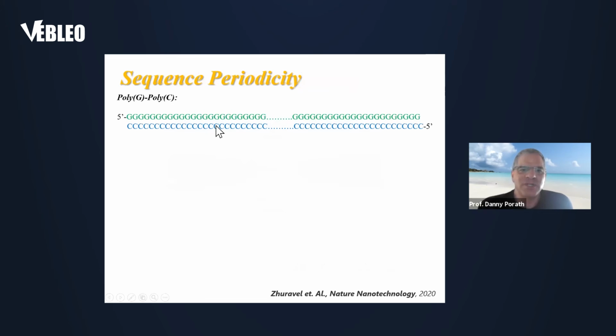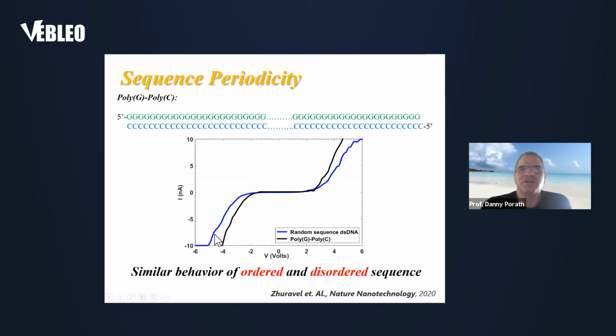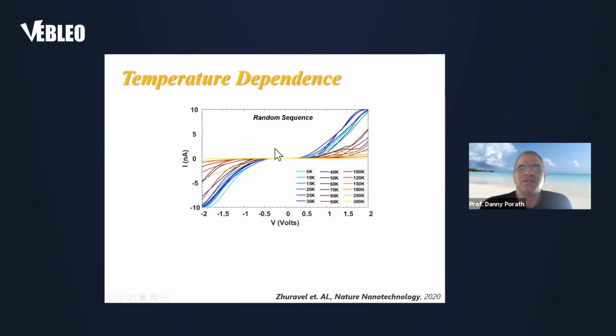Then we went forward and we measured a homogeneous sequence. We naively assumed that we will get a better current because it's all guanine bases with the lowest oxidation potential. And also it is homogeneous, so the levels could be aligned. And surprisingly, we got currents that were roughly similar to the previous measurement. So that was very strange and unexpected. So then we checked the temperature dependence to address the mechanism of hopping versus tunneling, as we mentioned before.